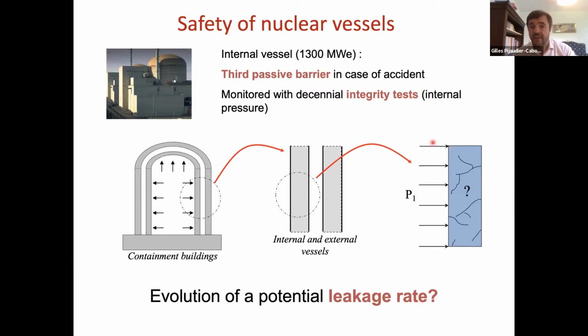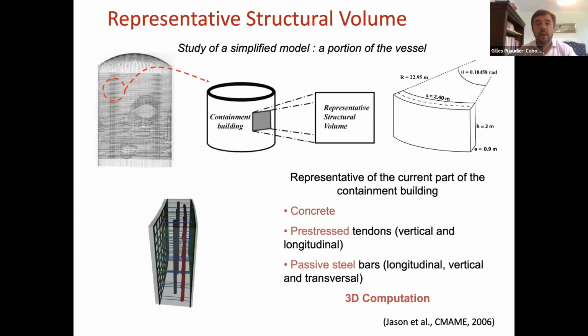Here you would expect a strong coupling, at least between the solid phase and the fluid phase. The solid phase is made to prevent the fluid from going from inside to outside the vessel. So typically, what is being done - and it has probably been improved a bit, but not much, because these are rather complex structures pre-stressed with passive steel bars and concrete - is just considering a representative volume like this, then you apply the pressure inside and measure the leakage rate outside.